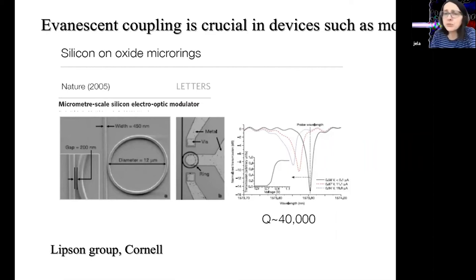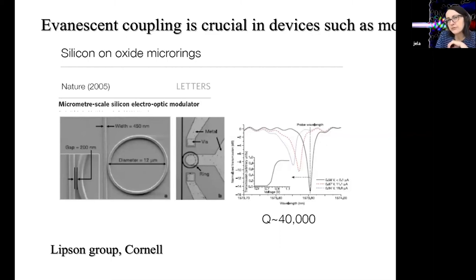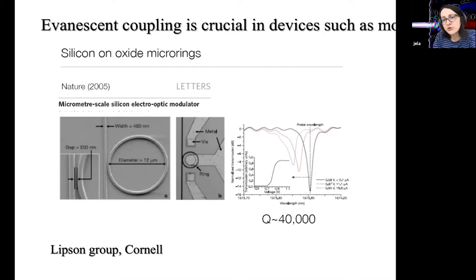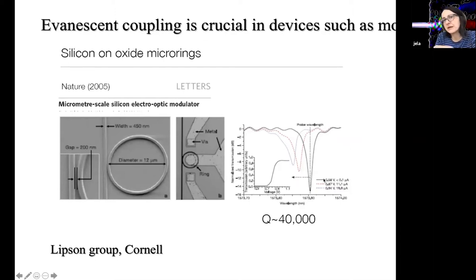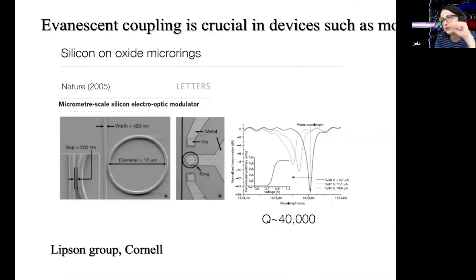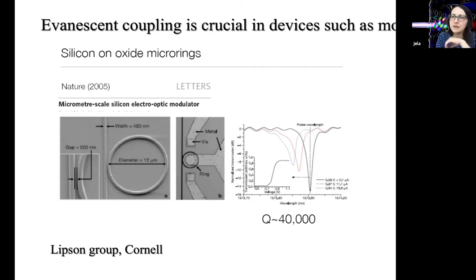The problem is that in silicon, the decay of carrier recombination takes a while because it's an indirect bandgap semiconductor. So the modulator would not normally operate very fast. People address this by sweeping the generated free carriers with a PIN junction to speed up the system, and people have demonstrated gigahertz operation using sweeping of free carriers.